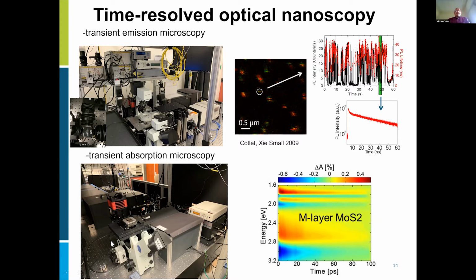It's a pump-probe experiment where basically we investigate the excited state absorption of a material. In this particular case, an example is shown for a monolayer MoS2, where this image shows the ability to spectrally resolve, so energetically resolve, versus time resolve excitons in a monolayer MoS2, basically. At various times, we can see different excitons in this material. So the combination of these two techniques is very powerful in learning about ultrafast dynamics of these nanomaterials.